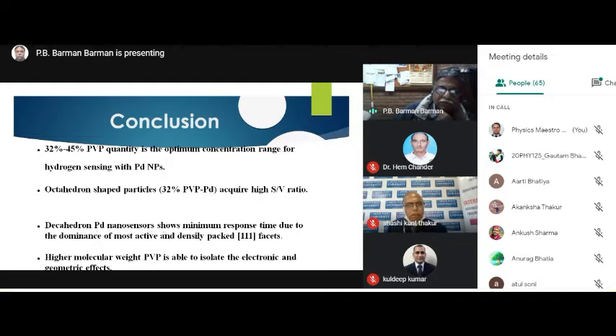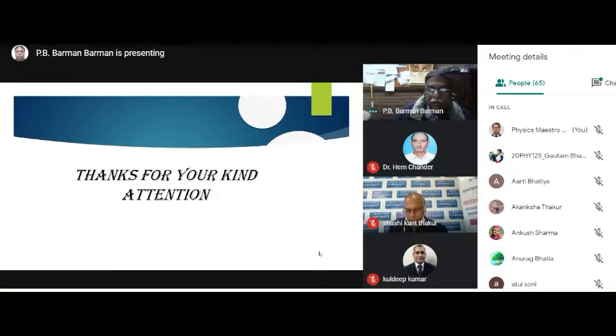The decahedron palladium nanosensor shows minimum response time due to the dominance of the most active and densely packed 111 facet, and higher molecular weight PVP is able to isolate the electronic and geometric effects. Practically, we are interested more in the geometric effect rather than the electronic effect.